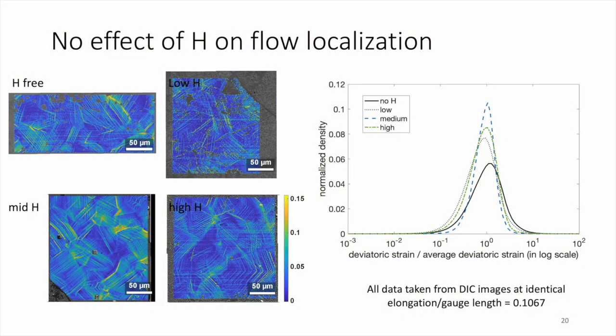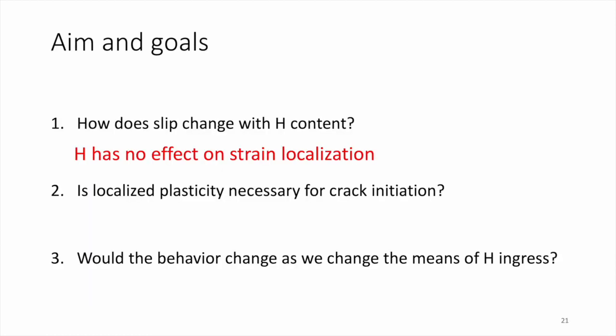Ours looks like this. You find the distributions for all four samples are relatively broad. This is consistent with our qualitative observation that flow is localized into discrete slip bands. Also, there are no monotonic trends in the shapes of these distributions as a function of hydrogen content. So the degree of localized plasticity in hydrogen-charged samples is comparable. So we can conclude that in this case, hydrogen has no effect on the strain localization. Do you see any trend?